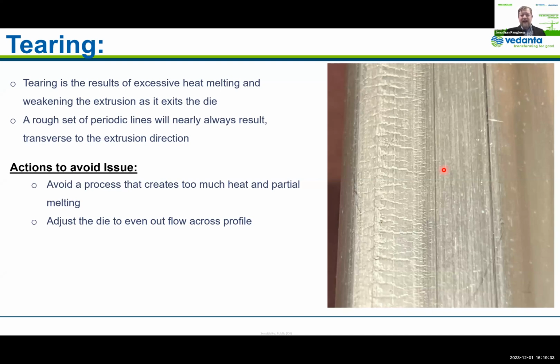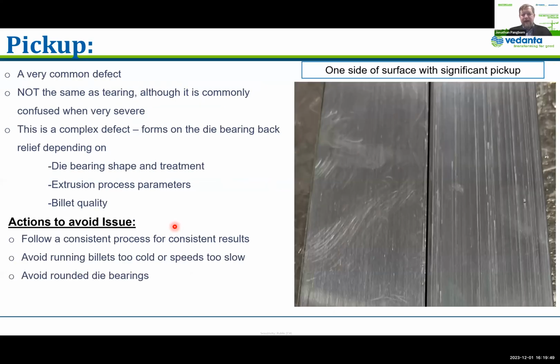I would encourage you also to look at dies. If you have a die that is sensitive to this, work with your die shop, work with your die vendors. Really what you're doing is trying to even out the flow across the profile to try to avoid this. Moving on into pickup. In some cases, very severe pickup is termed tearing, but I want to be careful to differentiate those because the processes by which those defects are formed are very different. So in this example, this isn't highly severe pickup, but this is starting to be a problem. In this case, this is a simple flat bar, and we have one side, and this is just some handling marks from people handling it, but basically this surface here is acceptable, and on the other side it's not acceptable due to this pickup.